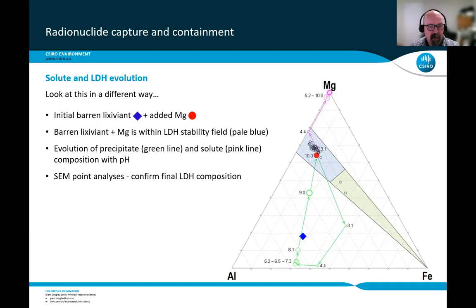If you look at the pink line now, again, we start at that point where we had the layered double hydroxide composition after the magnesium was added. As you look at that pink line, the solute composition starts to move away from the iron, again, because now you're depleting the solute with iron, and then starts to move away from the aluminium after pH 4.4. And as you move up to pH 10, you've depleted all the aluminium, you've depleted all the iron, and then you've got a small amount of magnesium occurring in the final solute. So this is just a really nice way to look at the behavior and the composition of both the solid and the solute as you form the layered double hydroxide. And thankfully, we end up with a final composition that's pretty similar to where we started and what we wanted to form.